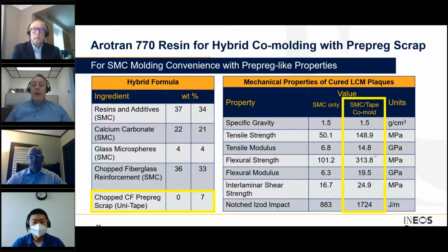So these data dramatically demonstrate that even a small amount of continuous fiber, when judiciously placed, can enhance the mechanical performance of an SMC application to a really surprising degree, making a lightweight, high-performance part. In the case that the continuous fiber is prepreg scrap, the carbon footprint of the manufacturing operations is also made just that much smaller.